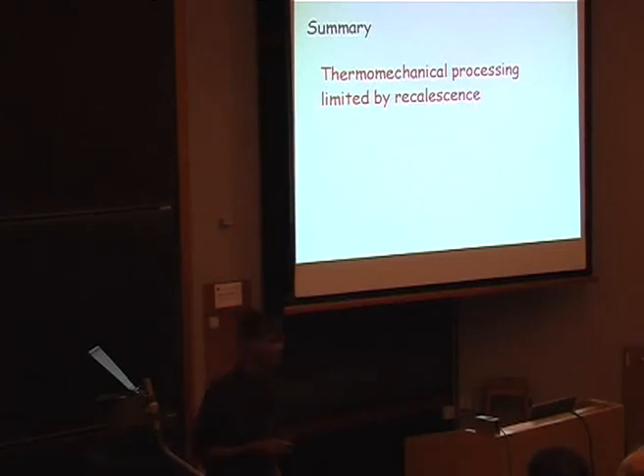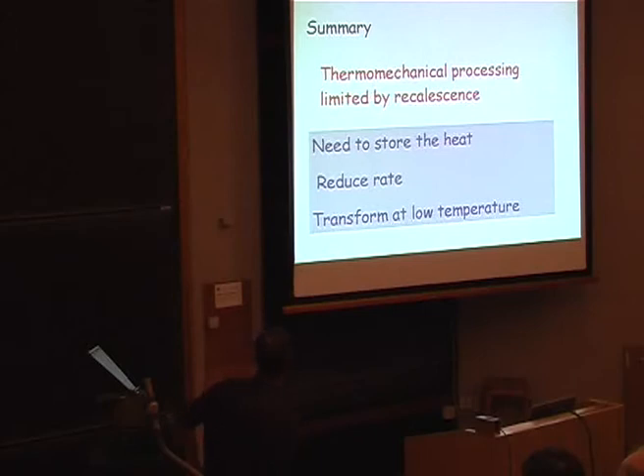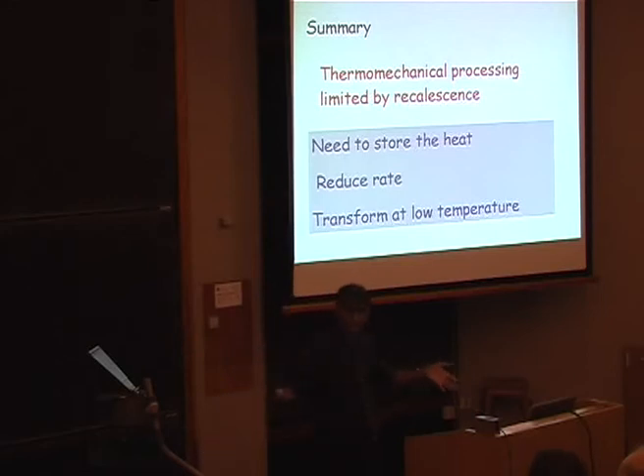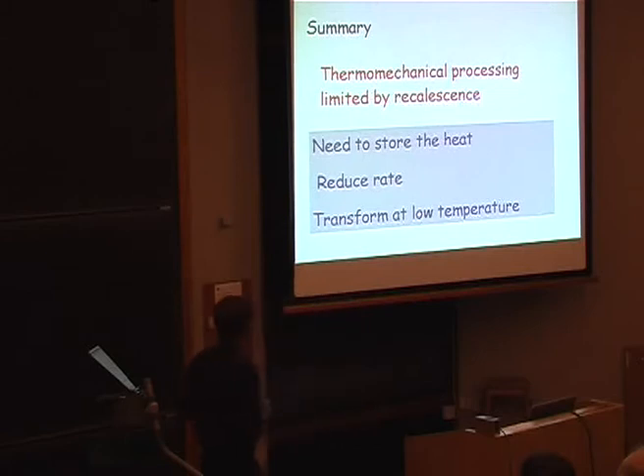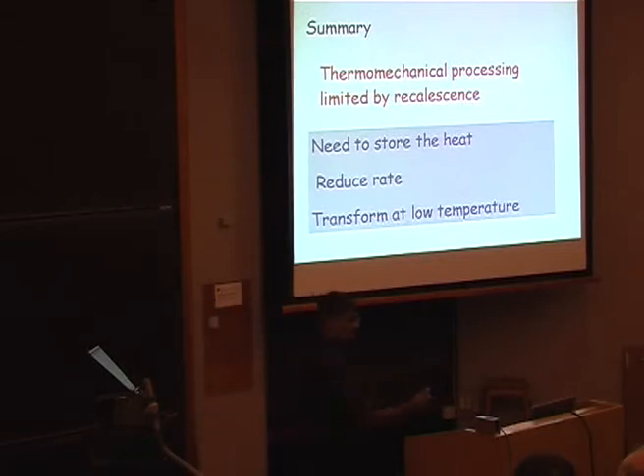So how do we go about making a bulk nanostructured material? Well, the first thing is that we do want to transform at a lower temperature because we need that free energy to create smaller and smaller crystals. But we need to somehow store the heat of transformation within the material itself. We need to reduce the rate at which the crystals form so that the heat can be dissipated. And all that amounts to transforming at a low temperature.